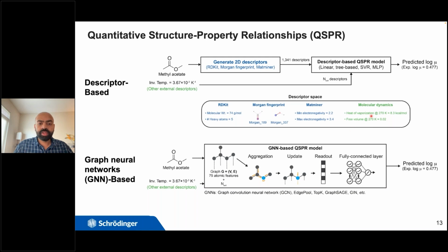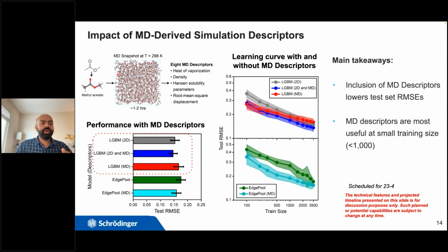So we combine the molecular dynamics descriptors with all these 2D descriptors, and we also combine the molecular dynamics descriptors with the graph-based approaches. Here you can see on the top left the snapshot of an MD trajectory that was used to generate the descriptors for methyl acetate. We have a particular workflow of running equilibration, running NVT and then NPT followed by a 20 nanosecond NVT run to get these descriptors. The descriptors that we use are around 8 MD descriptors: heat of vaporization, density, the different Hansen solubility parameters, and also the RMSD. So these are the descriptors that we extracted from molecular dynamics.